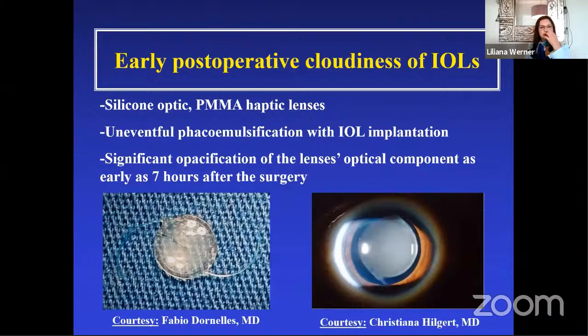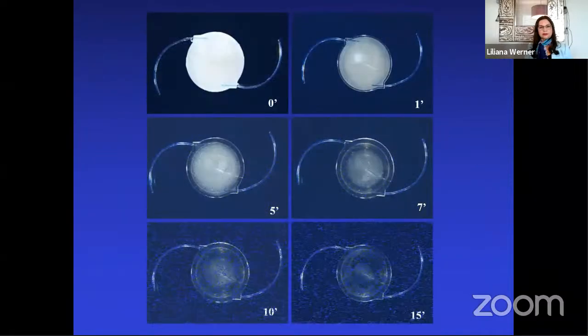Let us talk a little bit about very interesting cases of opacification of 3-piece silicone lenses, which was observed very early postoperatively. These cases came from Brazil. After uneventful surgery, significant optic opacification was observed as early as 7 hours after surgery. The lenses were submitted to our laboratory for analysis, immersed in solution. During examination, as the lenses were drying, the optic opacification decreased until it completely disappeared.